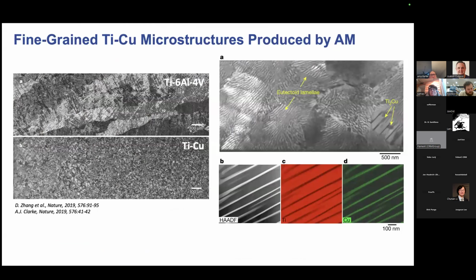So the last Ti example I have is more of a solid state example. Ti-6Al-4V tends to have these elongated columnar grains, where it was shown by a recent Nature publication that Ti-Cu produces these refined grains, and that was thought to be due to the constitutional supercooling during solidification.